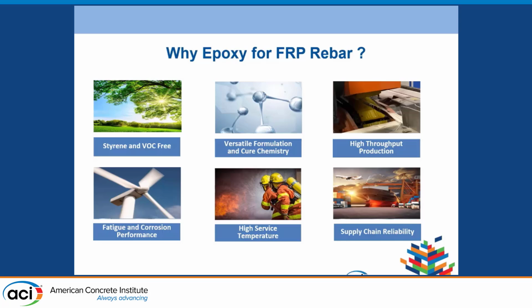Epoxy is also well known as a protective coating for metal, so this corrosion resistance fits well with FRP rebar applications. Epoxy is also the resin matrix choice for windmill blades, due to its high fatigue performance. Epoxy is also very compatible with different fiber systems, like glass fiber or carbon fiber, so it is a very versatile system. Typically, epoxy can offer higher Tg than vinyl ester or unsaturated polyester. This is good for many tests, for example the serious corrosion resistance test ASTM D7957, which is tested at 60 degrees C. The high Tg will help in the testing. And epoxy is well available all over the world, so it provides supply chain reliability for the industry.